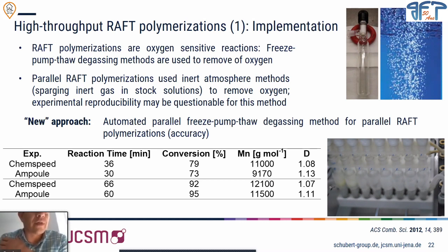They degas it with the freeze pump method, the conventional one, with ampoules, and I use the same mixture to put in the Chemspeed and apply this method. At the end of the day, we got very similar results. He put his ampoules in the oil bath, and I ran the Chemspeed at the same temperature. Let's say reaction times were similar.